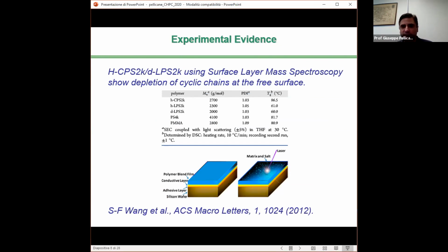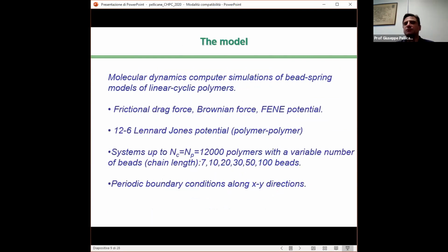So in a recent experimental work, by considering polystyrene polymers with linear and cyclic architecture, these authors showed evidence of enhancement of linear polymers at the interface and corresponding depletion of cyclic polymers in the regime of low cyclic polymer composition. Motivated by this work, we performed extensive molecular dynamics simulations of bead-spring models of linear and cyclic polymers, where Stokes and Brownian forces act on polymer beads, so as to simulate the effect of the solvent, and polymer beads interact among themselves with the Lennard-Jones 12-6 potential. Periodic boundary conditions were applied along the X and Y directions of the simulation box, while at low and high Z, polymers get exposed to empty space and two vacuum-blend interfaces are formed.